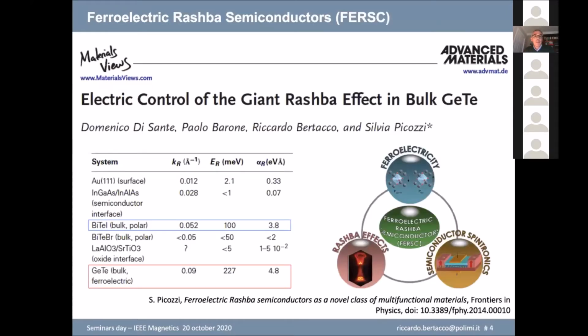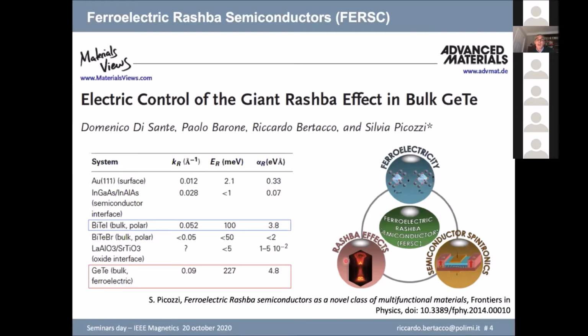So let's start with the introduction of ferroelectric Rashba semiconductors. These are a class of materials introduced by Silvia Picozzi in these theoretical papers, in which you have the coexistence of three features: ferroelectricity first, but also the fact that you're dealing with a semiconductor, which is somehow unusual because in general ferroelectric materials are oxides, insulating materials, and the presence of Rashba effects. So you have these three corners here, ferroelectricity, semiconductivity, Rashba effect, all combined in the same material, with the possibility of achieving new functionalities.